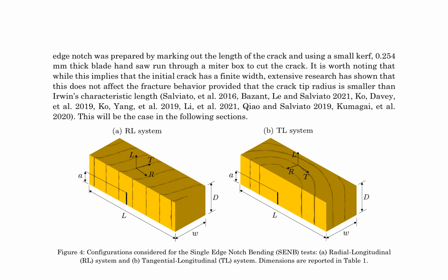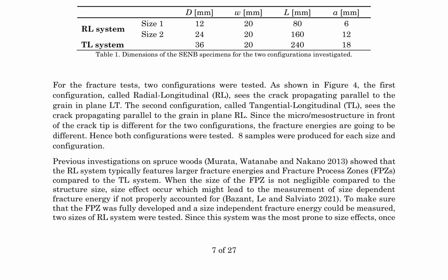The dimensions of the SENB specimens for both configurations are presented in Table 1, with 2 sizes tested for the RL system and 1 size for the TL system. 8 samples were produced for each size and configuration to ensure reliable results. Previous research on spruce wood has shown that the RL system typically exhibits larger fracture energies and fracture process zones, FPZs, compared to the TL system. To account for potential size effects, 2 sizes of the RL system were tested, as this system is more prone to size effects, allowing for the measurement of size-independent fracture energy and ensuring the FPZ is fully developed.